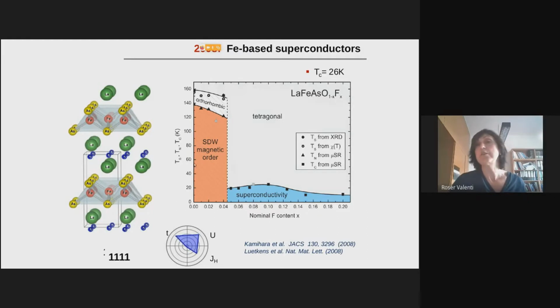They show a long-range magnetic order. However, the difference between this class of materials and the high TC cuprates is that the parent compounds are not insulators. They are still metallic. So they are metallic. When one then dopes the system or puts the system under pressure, they become superconductors.